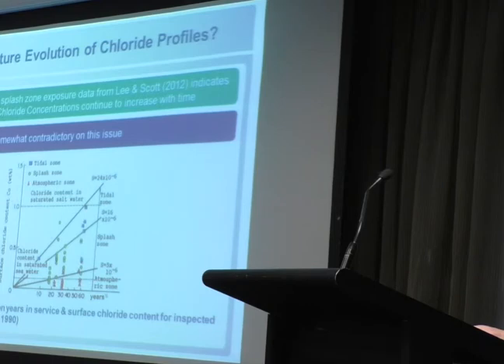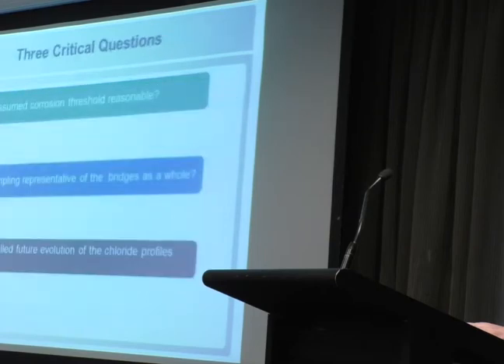That's some data from Uji, which suggests that it does increase with time and the rate of increase depends on the exposure environment. It's interesting to me that he suggests that the rate of increase is most pronounced for concrete in the tidal zone, because other researchers will tell you that the concentration becomes constant very quickly if the concrete is exposed to daily tidal inundation. So it's hard to know what to believe, but I think you've got to say that conservatively you have to assume that there is some increase in the concentration with time.